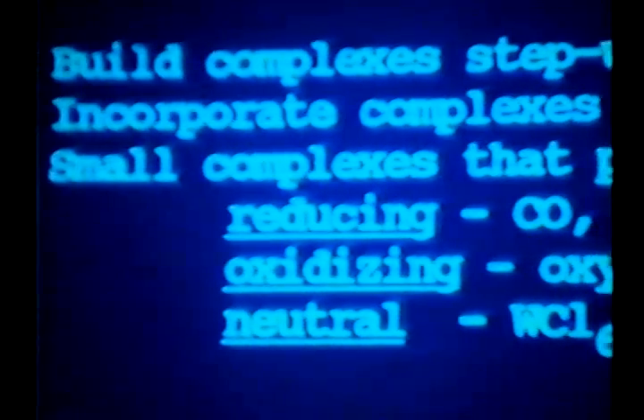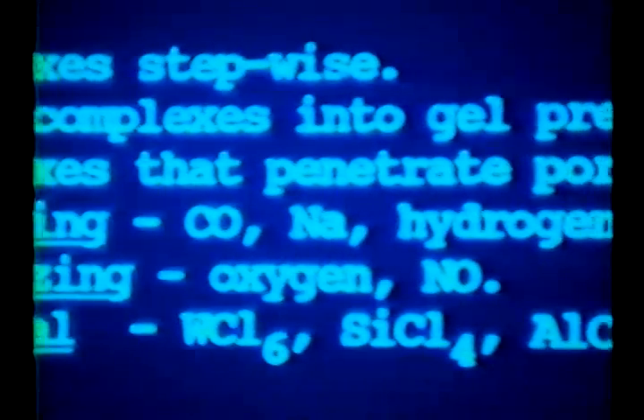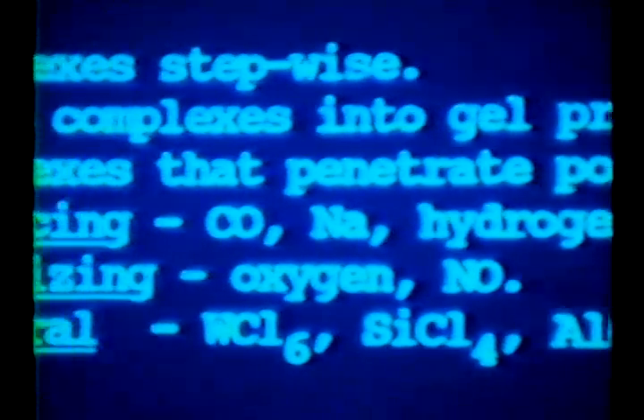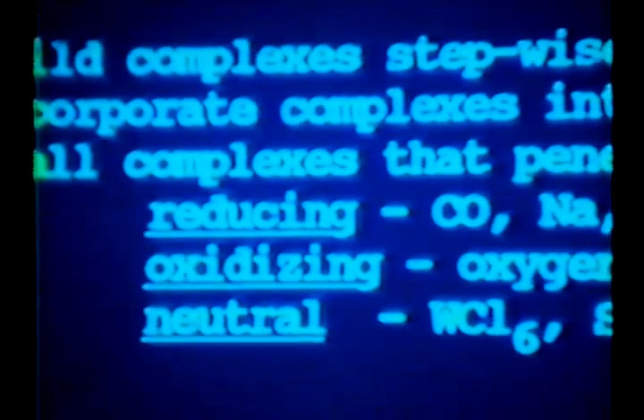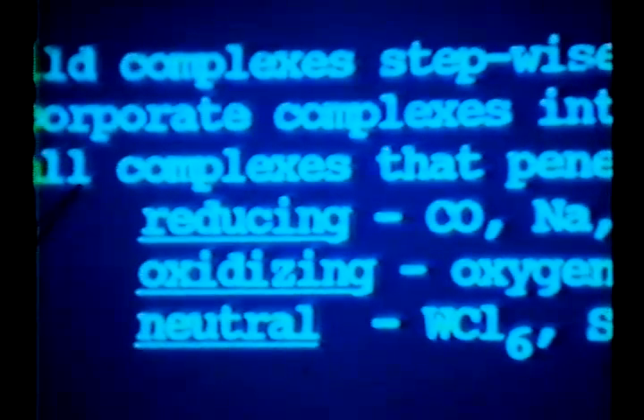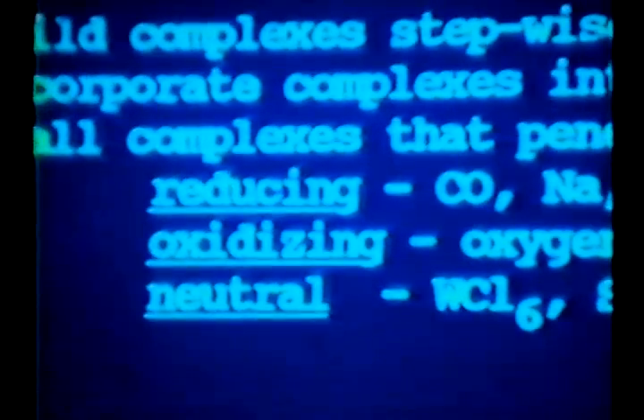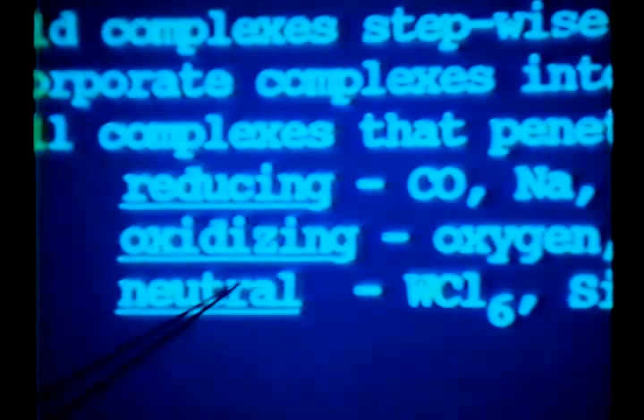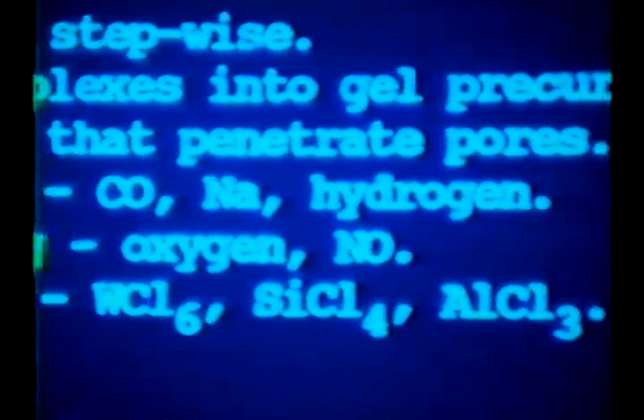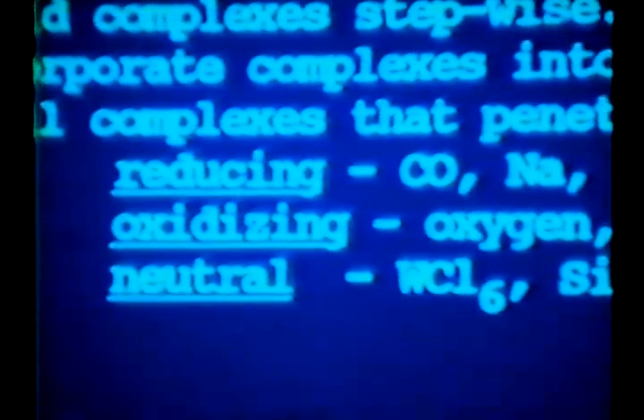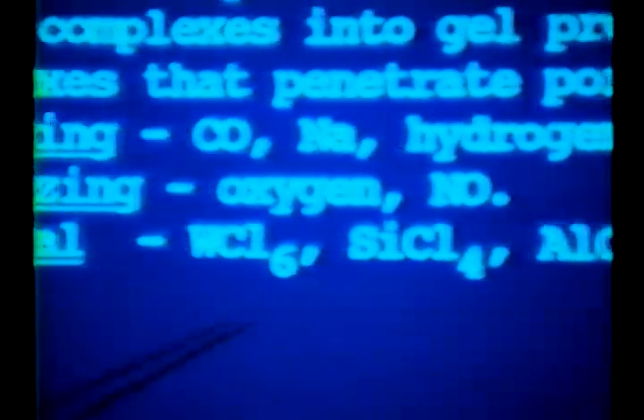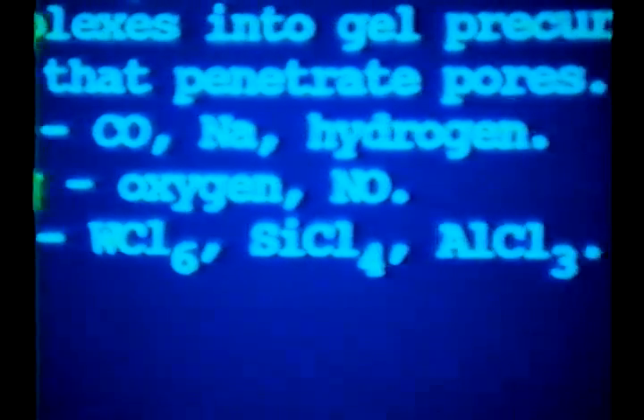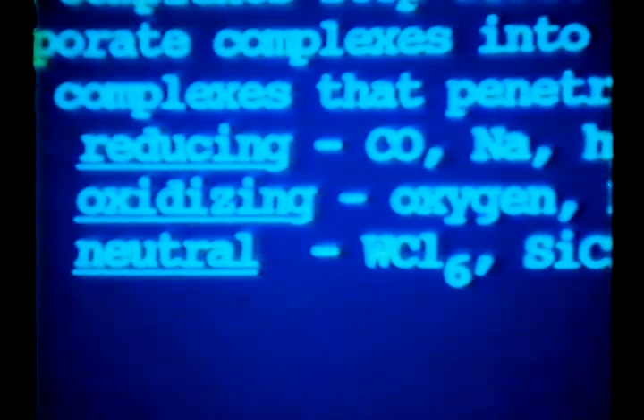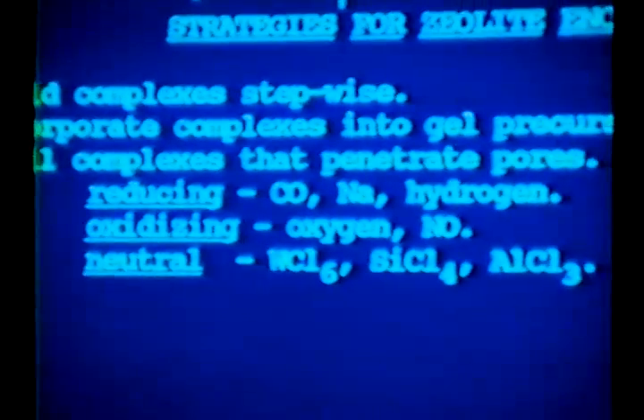Some people have tried to incorporate complexes into a zeolite gel and try to grow the zeolite around the metal. It's useful in ZSM5 and platinum in that case, platinum ZSM5 materials. And also, you try to use very small complexes that you know can enter the pores. And the types of reagents you might want to use to treat the materials might be for reducing or oxidizing or neutral type species, such as carbon monoxide or hydrogen, oxygen, or salt type materials. So you can treat these materials, metal complexes, with all these different agents.